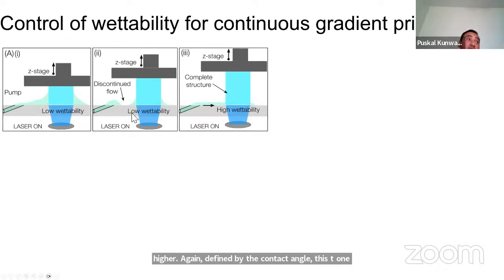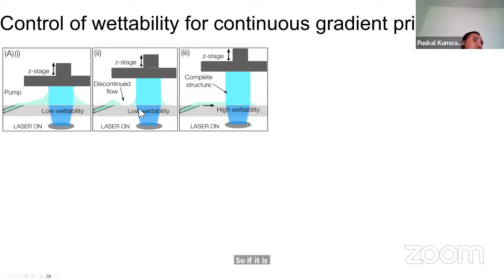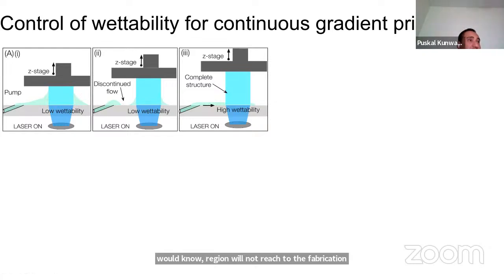Now you could try to control this volume by lowering the pump rate or flow rate. However, you saw in video one that this could discontinue flow as you decrease the pump rate. If the flow is discontinued, then the resin will not reach the fabrication area or this meniscus region, and the structure will not be fully printed. So that way you cannot decrease the flow rate from here.